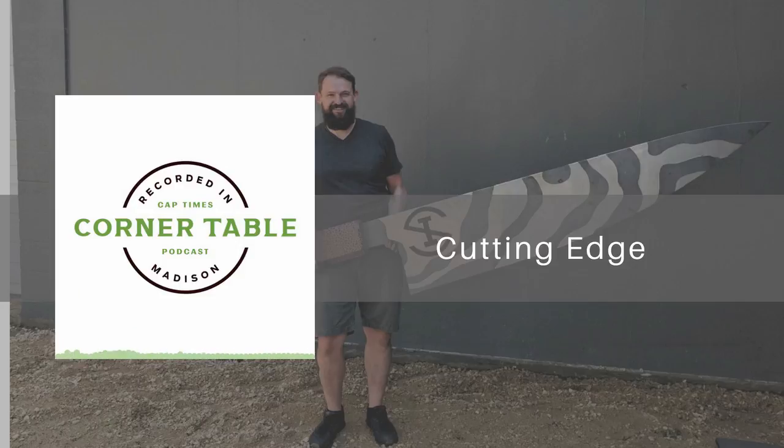One of the things that's really eye-catching about your knives is some of the patterns that you get in those. How do you make the patterns in the blade? There's a whole process involved with that. For something like a Damascus knife, I start with 2 different steels in a raw bar stock and stack them in alternating layers. And I take that stack and heat it up in the forge until it's yellow heat. When it's reached temperature, then I hammer those together, and that process is called forge welding. And then it's a solid piece of metal after that.